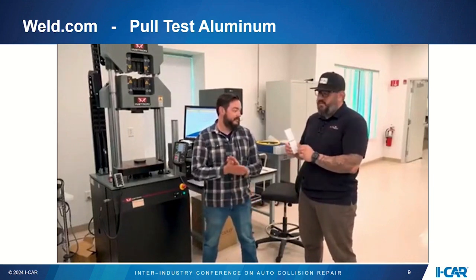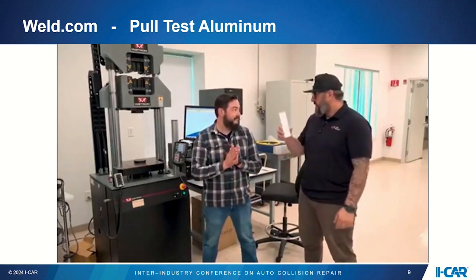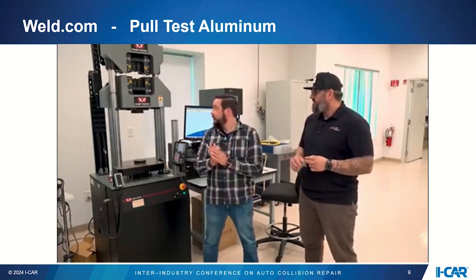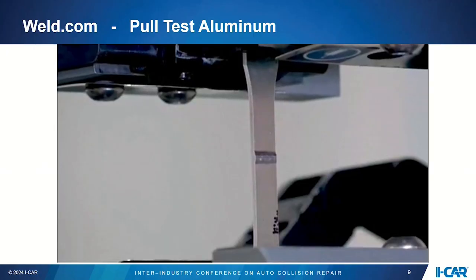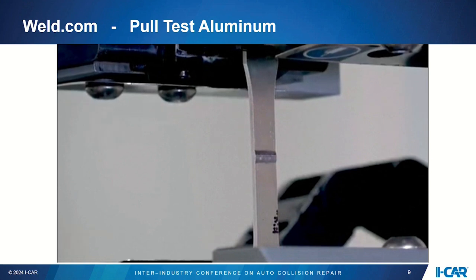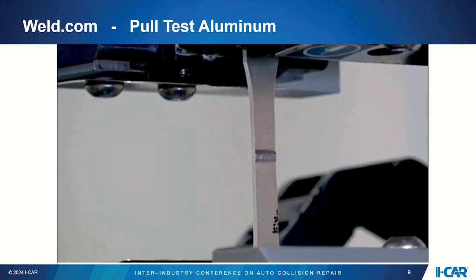Okay. Nice. And I see on a lot of the forums online, people see laser welding for the first time, and it kind of looks like voodoo. And they're like, well, that can't be strong. It's such a small weld. That's just weaker than normal welding, or this is just trickery, camera work, whatever. And no, it's the real deal. These panels here are fully fused together, even though that weld pool is only a couple of millimeters wide.